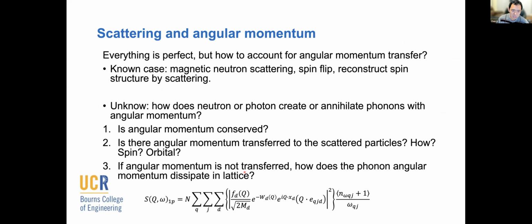Before we show the data, I want to quickly go through the dynamic structure factor for a one-phonon scattering process with X-rays. One important take-home message about the formalism we've been using so far is that it was derived completely from the neutron perspective, and there isn't any consideration in terms of polarization for X-rays. As you can see, the dot product is between the phonon eigenvectors and the Q vector, the change of the K vectors of the scattered photon in this process. So there are actually a lot of questions going on. For example, when we scatter one photon off a phonon, when the phonon contains angular momentum, is there a transfer of spin or angular momentum in that scattering process?